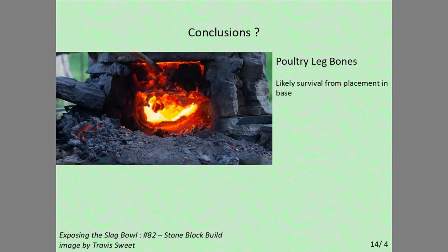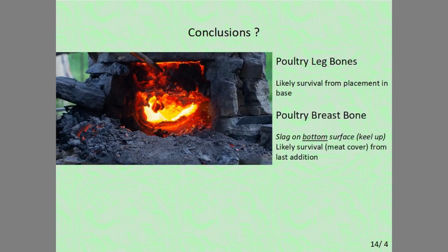What conclusions might be drawn from the recovered bones? First of all, the poultry leg bones were found within the charcoal fines. This suggests they were likely survivals from their placement in the base at the start of the experiment. All the poultry breastbone pieces were encased in meat and been placed in the furnace with the keel, the central rib, side upwards. This suggests that the piece recovered with slag on its bottom surface had actually survived its descent through the furnace from the last addition of bone.